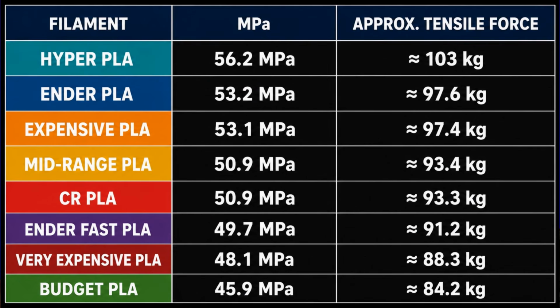What you're seeing now shows us the approximate tensile strength of the test models after the formula calculation has been done. Hyper PLA was already in first place with 56.2 megapascals. Its approximate tensile strength corresponds to 103 kilograms. As you can see, it continued to decrease. We didn't change the previous ranking at all. The cheapest PLA, on the other hand, yielded a result of 45.9 megapascals. Its approximate tensile strength was 84.2 kilograms.